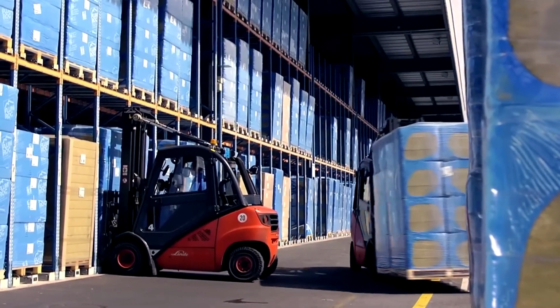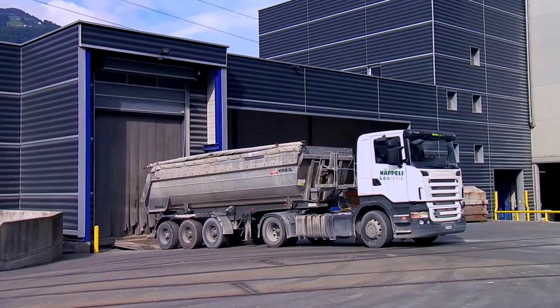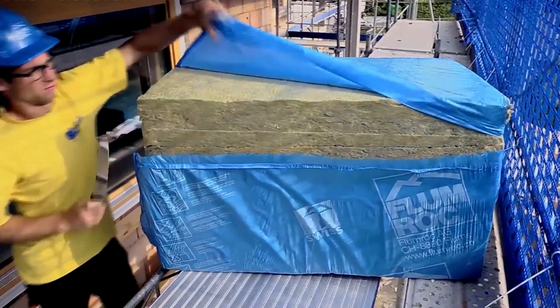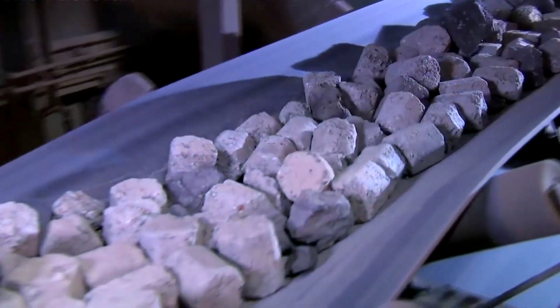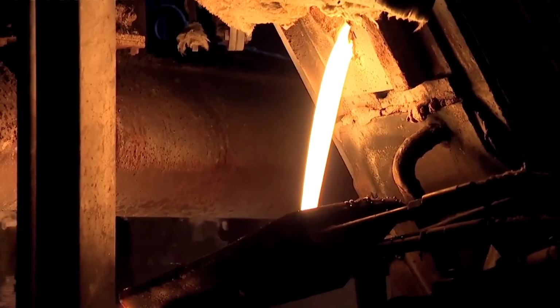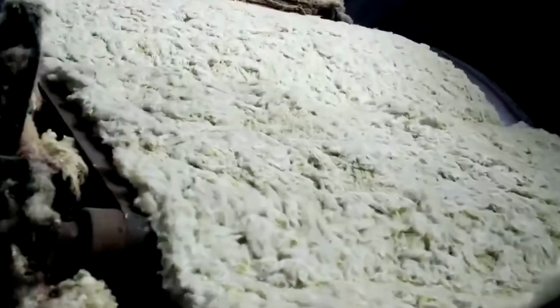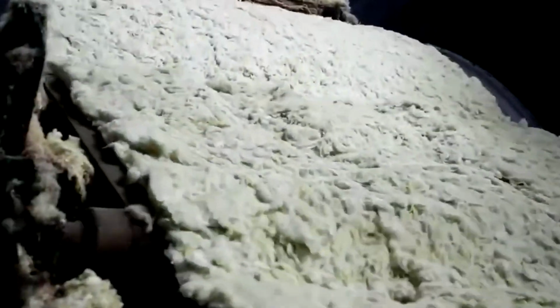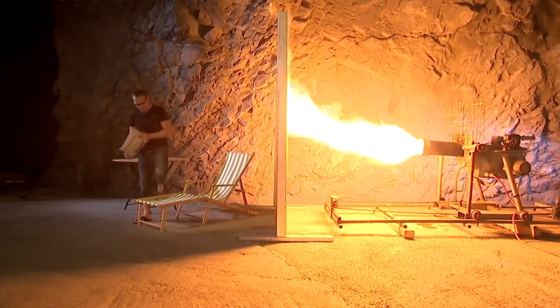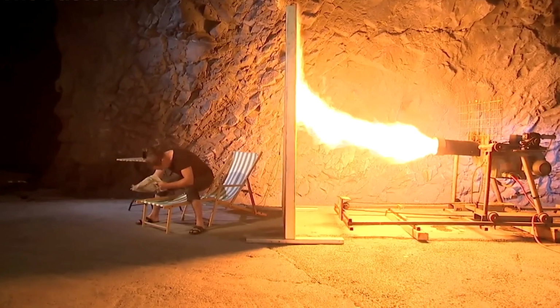A flamethrower blasts the surface with temperatures around 1200 degrees Celsius, while a person can sit directly behind it, completely unaffected. After inspection is complete, the insulation boards are carefully wrapped in heavy-duty plastic film. Automated machines seal each block, protecting it from moisture and damage during transit. The packages are then secured with an additional layer of shrink wrap to keep them stable when stacked.